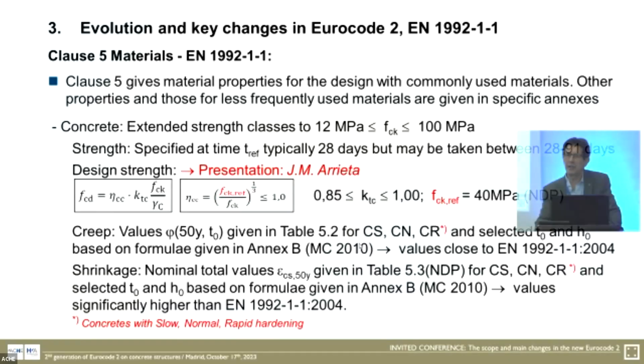Concrete, we have increased the maximum compressive strength class to 100 MPa cylinder strength, and we have modified the definition of the design strength. Today it's alpha_cc times f_ck divided by gamma_c. And you see we have replaced here the alpha_cc now with two coefficients. k_tc is a coefficient to consider the effect of sustained loads, Rüsch effect, and eta_cc is a coefficient to consider the increased brittleness of higher strength concretes. You see the formula for this coefficient eta_cc over here.